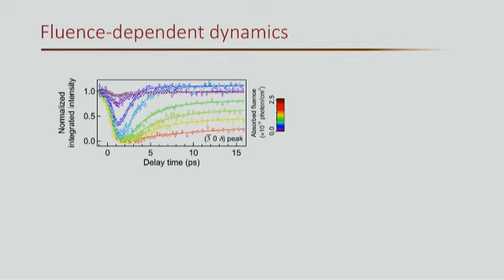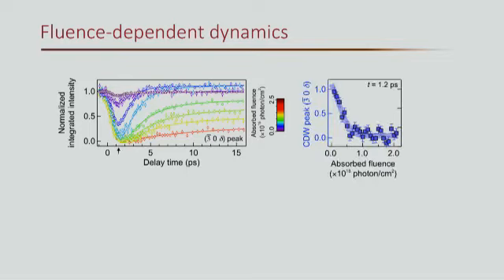This is basically what we did. We tuned the pump laser excitation fluence. We observed that at very low excitations, there's a very tiny suppression of the intensity. But if we pump harder and harder, the CDW peak gets essentially suppressed in terms of its intensity. You can summarize this by sitting at around 1.2 picoseconds and plotting the intensity as a function of fluence, which is summarized in the plot on the right-hand side. Again, we see that around 2.5-ish in terms of the number of photons incident per square centimeter, we see almost a full destruction of the intensity of the CDW peak, which is below our detection limit. So this is all good. It's all within expectation. You pump harder, you suppress the intensity more.